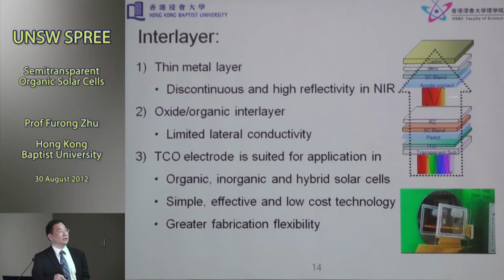So therefore, you see that you want something in between to connect. When the light passes through, part of the light will be absorbed by the front cell, and the light that cannot be absorbed or utilized by the front cell, you want it to 100% penetrate through to be captured by the rear cell. If you have an interlayer which reflects near infrared light, it basically blocks the light, so you won't get much of the light penetrating through the first cell. So this is something that we really need to look into if we look for high efficiency organic solar cells.